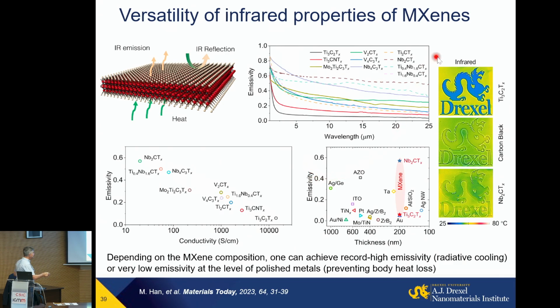And I should probably wrap up within 5 minutes to keep it within an hour or less. If you look at different MXenes, some of them, Ti3C2, for example, has very low emissivity compared to polished metal, like gold. Some others, like niobium carbide, are very good emitters, very good for space heaters, for example. They will emit heat. But what is interesting, this material is among the materials with the lowest emissivity, but it has thermal conductivity 3 orders of magnitude lower compared to gold. As a result, you can put on the surface of a hot plate, in this case heated to 80 degrees C, a 200 nanometer printed film.